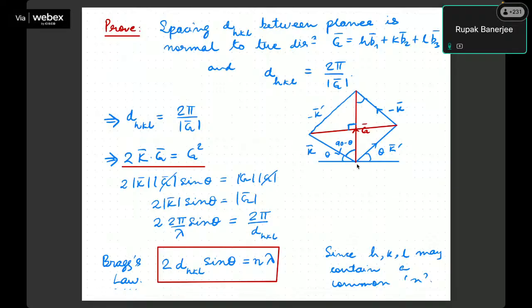You see this is our direction of incoming X-ray scattering, exit X-ray scattering. The distance between them is delta k, and we know now that delta k equals G. So if d_hkl is 2π by G and 2k dot G equals G squared, you expand this: 2k times G sine theta equals G times G, 2k sine theta equals G. You know what k is. K is a wave vector, so it is 2π by lambda. So 2 times 2π by lambda sine theta is 2π by d_hkl, and voila, that is what you get: 2 d_hkl sine theta equals n lambda.